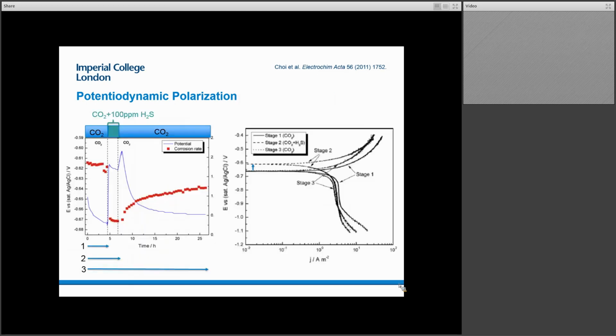Okay. So with that in mind, we've got these three stages. We're talking about what's happening at each stage, and with respect to the conditions under which we're encouraging, in the cathodic scan, one set of reactions. By contrast, we're encouraging a different set of reactions when we employ the anodic scan. And so there's a number of things potentially to take away from this. You have the same graphic on the left of your screen showing the open circuit potential. And then on the right, you now have these potentiodynamic polarization curves. And so what becomes interesting is starting to think about these curves in the context of what we were just discussing, what the authors in this case believe is happening.